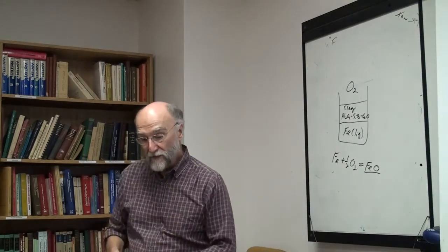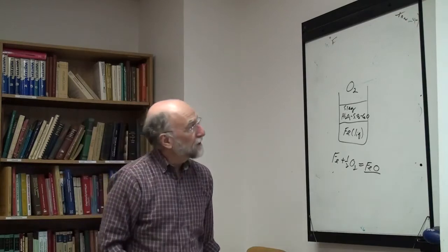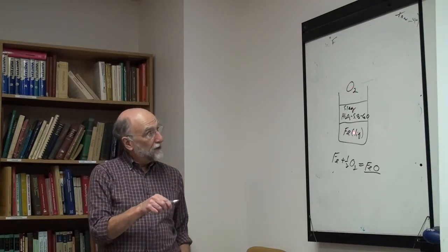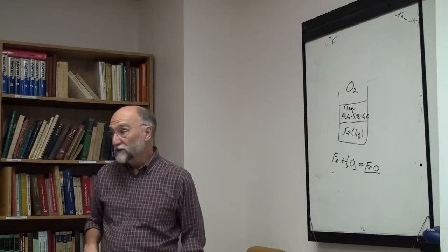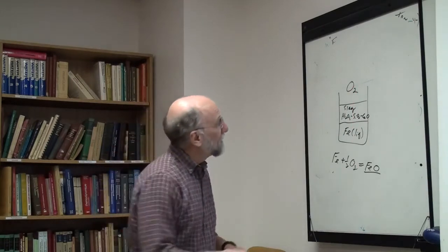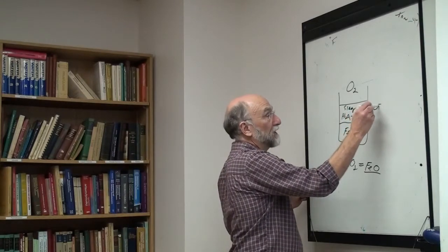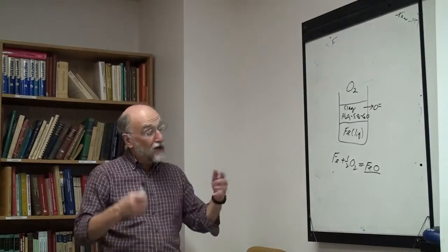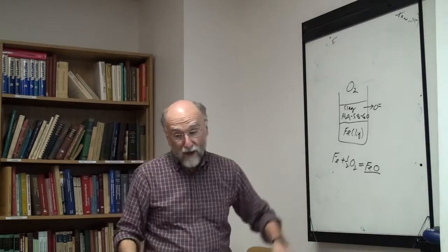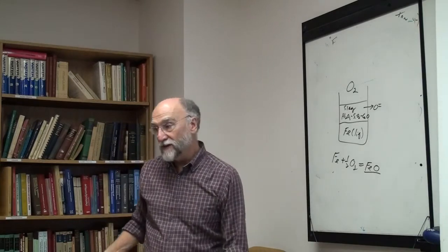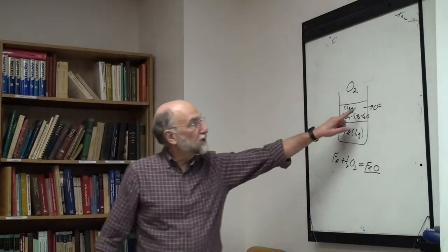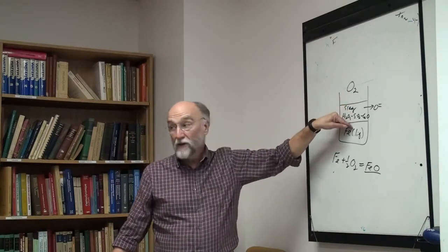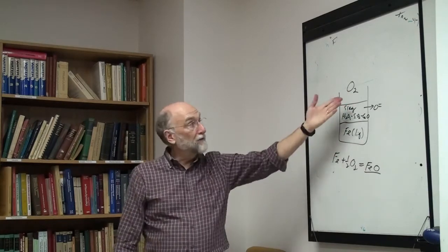Okay, but if you just set this thing up this way, you'll find there's no direct contact now between the oxygen and the iron. The reaction has to occur by diffusion. Now the slag is an ionic material. The slag contains oxygen ions, silica, calcium ions. It's an ionic conductor. The neutral oxygen, either as an atom or as a molecule, is extremely insoluble in here. So the oxygen cannot diffuse across the slag to the iron as a molecule. It would have to become an ion.